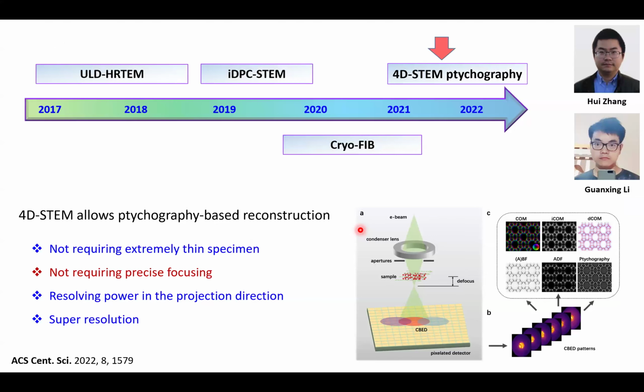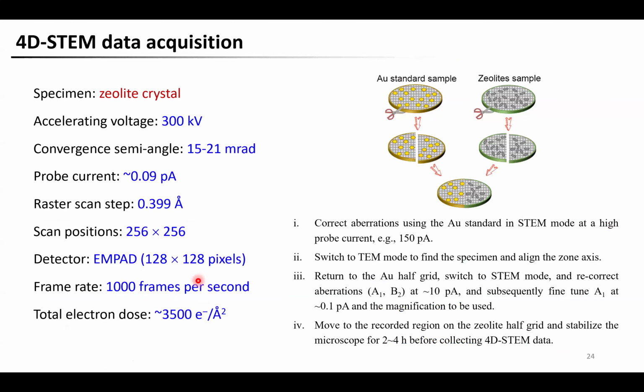With the development of ultra-fast pixelated electron detectors, 4D-STEM is becoming more and more popular. Ptychography is one of the most active research areas of 4D-STEM. Compared to conventional STEM, it has some advantages, including not requiring precise focusing to achieve high resolution. For sensitive materials, the ability to image without requiring precise focus is, of course, a significant advantage. So we began our experiments with zeolite samples because they are sensitive, but not extremely sensitive. Here are the conditions for our 4D-STEM data collection. I won't go into details, but just want to highlight that in this particular experiment, the total electron dose we used was approximately 3,500 electrons per square angstrom.